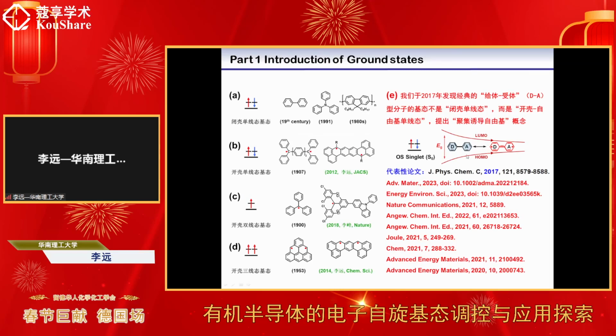And in our work, we proposed the aggregation-induced radical, and we proposed that the DA type organic semiconductors will also show the open shell singlet ground state. It's very challenging for us and for the scientists in this field to believe that this kind of compounds will show the open shell singlet ground state. And about 6 years ago, we published the first paper in the JPCC.